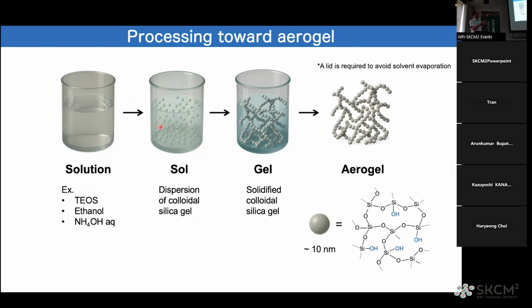Then you will have a sol, which means the dispersion of colloids in a liquid. And then after the reaction proceeds more, you can have a three-dimensionally solidified material that is solid, but it contains a lot of liquid inside. And after the drying, in this drying process, people often use supercritical drying using supercritical fluid at high pressure to avoid the shrinkage and cracking. So then you can have the aerogel, okay?